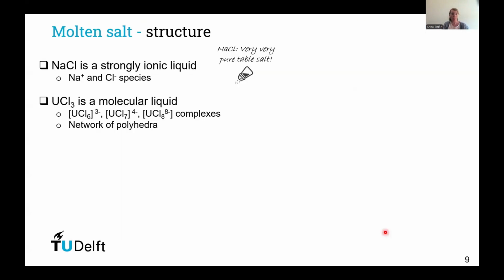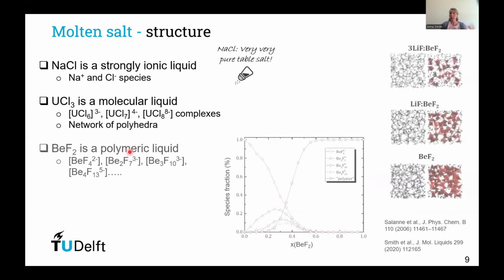To give you a bit of insight on the structure of molten salt, if we have purely sodium chloride, you could say table salt, we expect to have a strongly ionic liquid. But as soon as we add uranium trichloride in a mixture with sodium chloride, for instance, we form a molecular type of liquid. We form monomeric species, complexes that can have various coordination. And these polyhedra will start to form networks. They will start to form chains that will really become predominant when the concentration of uranium chloride, in this case, increases. And now if we had in the salt mixture something like beryllium fluoride, then we could expect to form really a polymeric liquid.